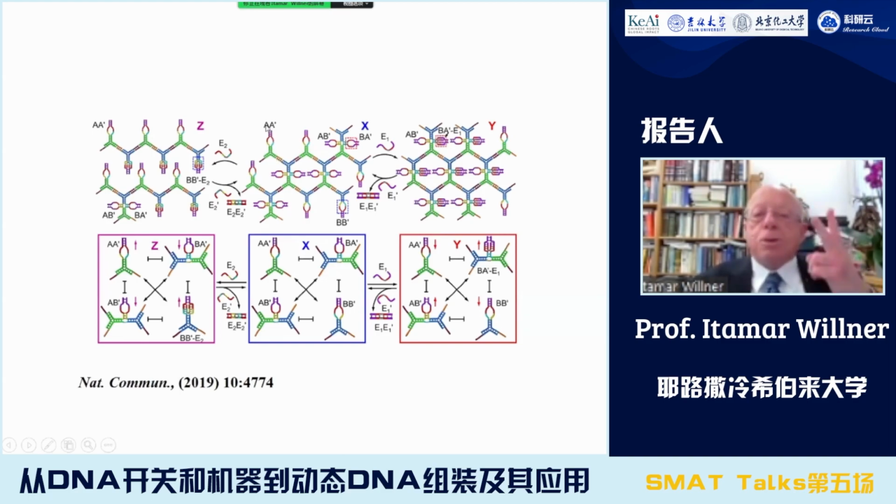Now note that the simple Y-shaped constituents don't form cross-linking units. Only the bifunctional Y-shaped components form cross-linking units. So the ratio between the Y-shaped and the bifunctional cross-linking Y-shaped units will control the stiffness of the gel.